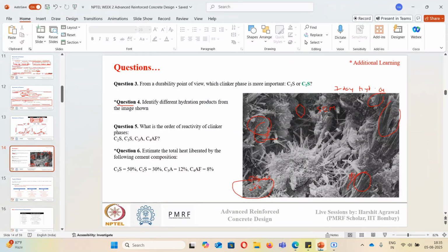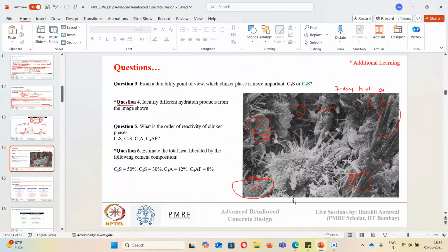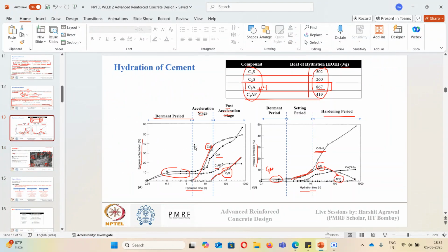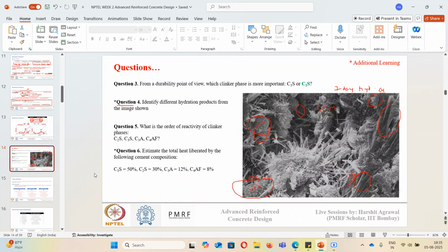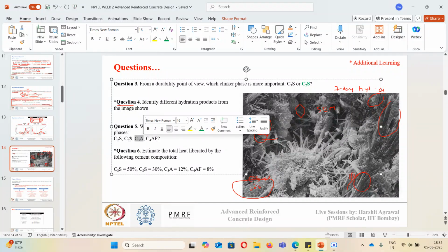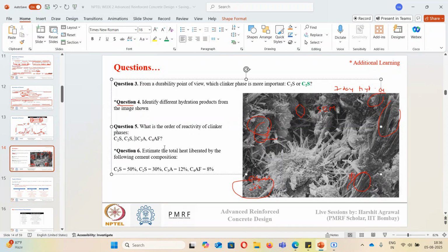Question number 5. What is the order of reactivity of clinker phases? We just saw this a while ago when we talked about the degree of hydration. The correct order of reactivity is C3A, which reacts quickly. Then we have C3S, then C4AF, and then C2S. C2S is slowest in terms of reaction. So C3A will be first, then C3S, then C4AF, and then C2S.